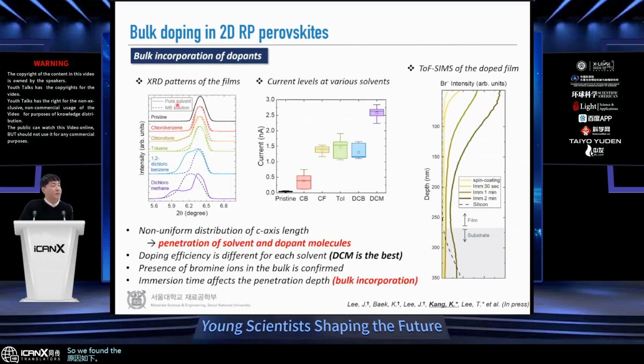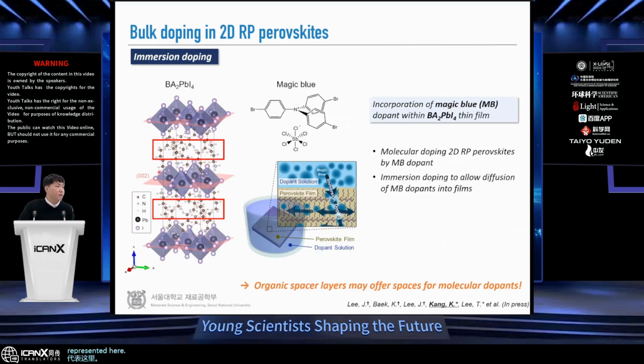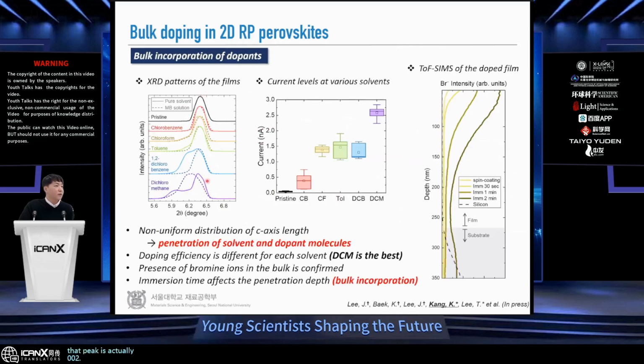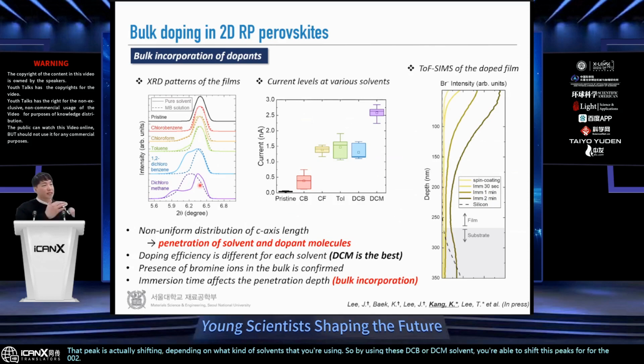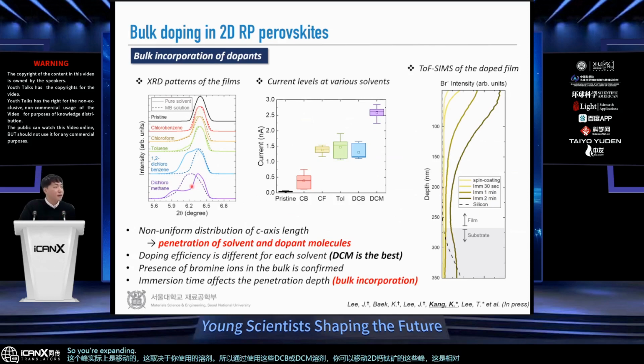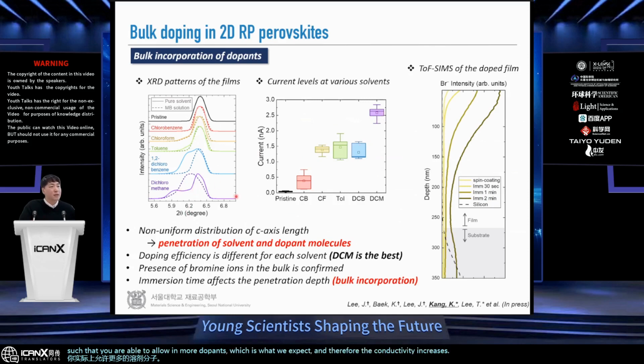the following. We found it interesting that by using different solvents, and therefore different solvent sizes, as well as their solubility in the organic spacers, this is representing the peak for layer distance. So layer spacing, people call it lamella spacing, the distance between the layers of n equals 1 perovskite, which is represented here, 002, that peak is actually shifting depending on what kind of solvent you're using. By using DCB or DCM solvent, you're able to shift these peaks for the 2D perovskites, which represents the fact that you're expanding these lamella. So you're expanding the layer spacing so that you are allowing in more solvent molecules, such that you are able to allow in more dopants, which is what we expect. And therefore, the conductivity increase was the largest for DCM.